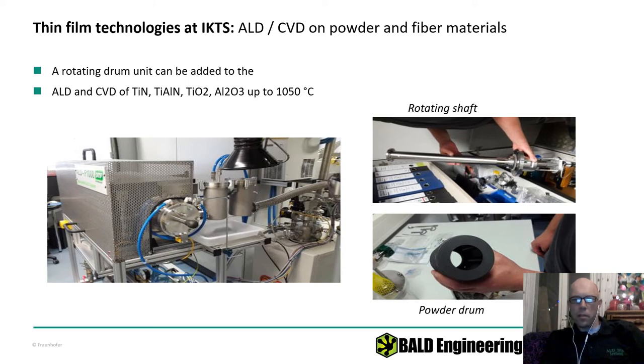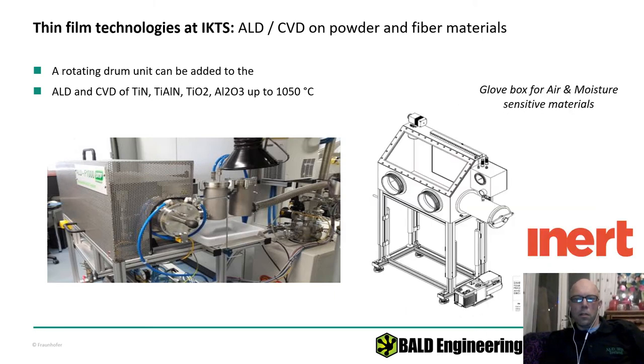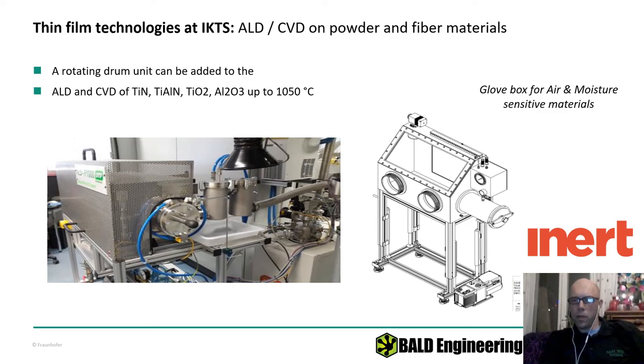The rotating drum is mounted on a shaft. It rotates at different speeds, and on the end is a graphite drum which we can swap and change the design of — this is where we place the powder. The whole shaft is inserted into the horizontal furnace and sealed with a Cajon O-ring. We can also hook up a glove box for battery powder research on hygroscopic cathode materials using inert atmosphere for loading and unloading.